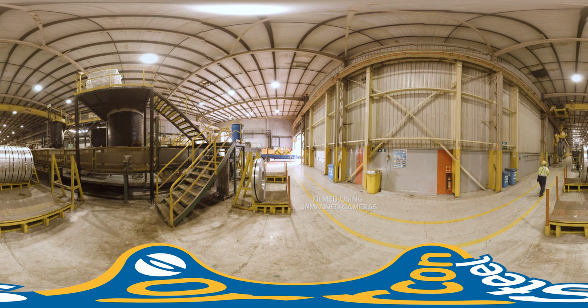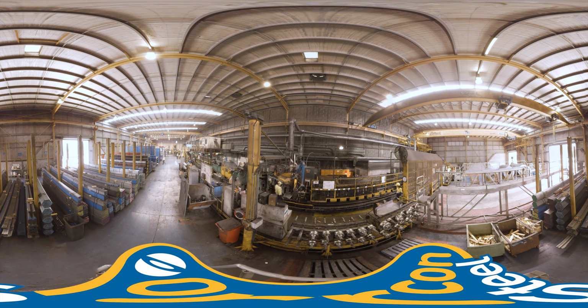The tube forming process starts with the slit coil being placed on the uncoiler, which presents the coil to the mill. The strip runs through a series of forming rolls that form the strip edges into a circular shape ready for welding. An induction welder heats the edges of the coil strip to over 1250 degrees Celsius. The edges are forged together when passed under pressure through the weld rolls to create a welded tube.